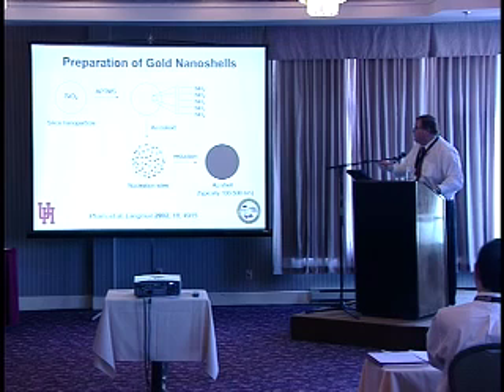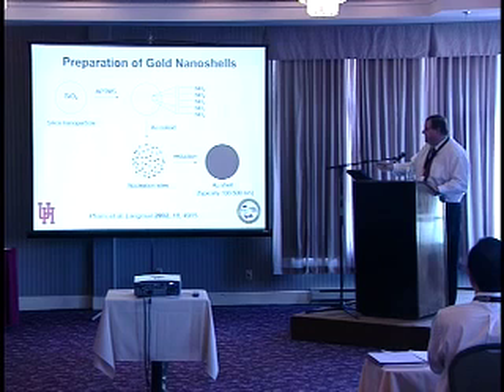To make a gold nanoshell, we typically start with a silica nanoparticle core, and we treat it with a silane agent to leave amino groups at the surface of the silica nanoparticle core. These amino groups are attractive towards small gold colloid particles, about 2 nanometers in diameter. And so then we have these silica core particles with these little tiny gold particles decorated on the outside, and we add a reducing agent in the presence of gold salt to then grow the gold shell. The gold seeds act as nucleation sites, and you get a complete shell.